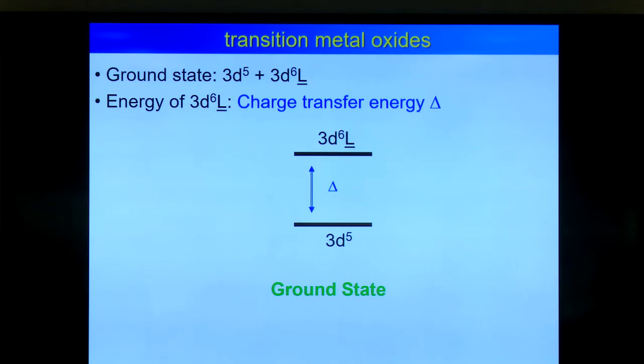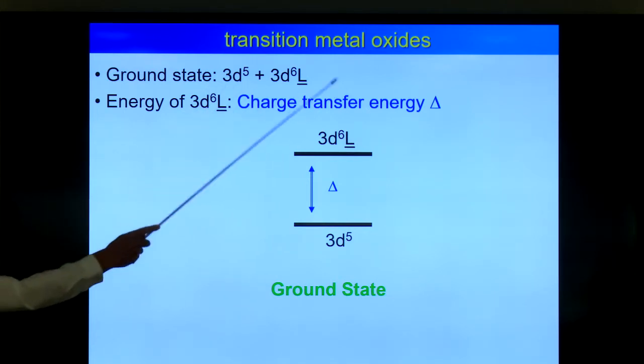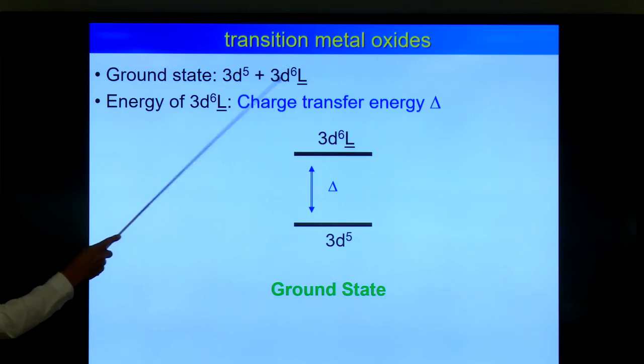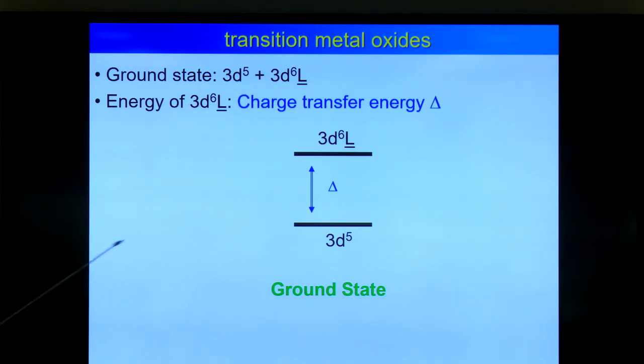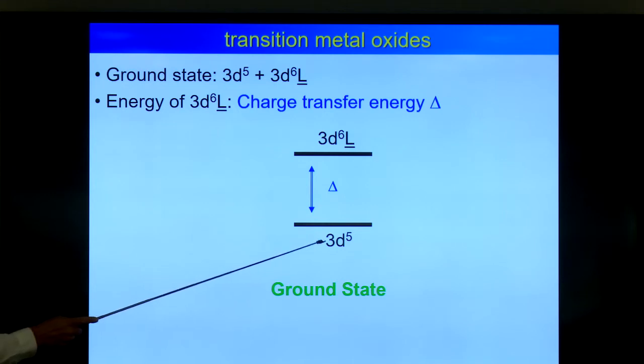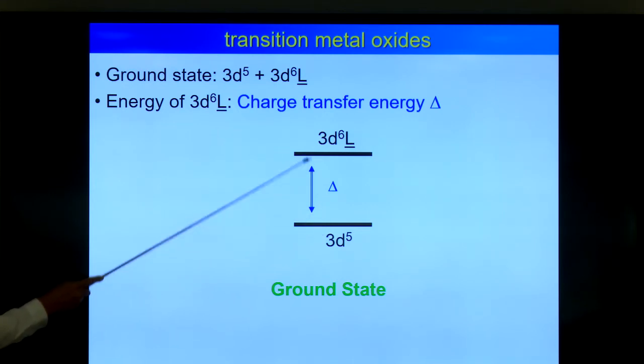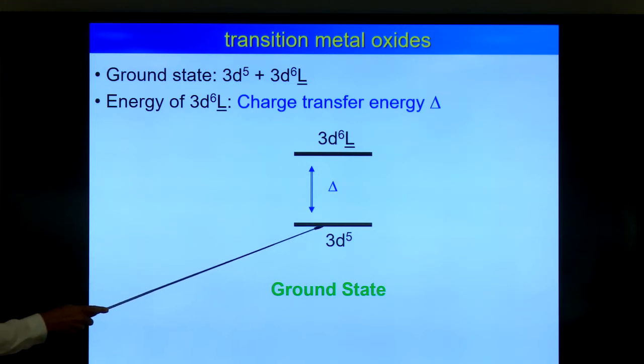And now you can make all kinds of excitations. So you can do metal-metal charge transfer, ligand-metal, and metal-ligand, and make a total ground state. If you do that, then it turns out that only these two are important for X-ray absorption. The other ones do not give a visible effect. So we now end up with a problem where we have d5 and d6 L-bar. That looks like a 2x2 problem, but actually it isn't. This is a multiplet of a few hundred states, and this also a few hundred states. So it's not 2x2, but it's a big calculation.